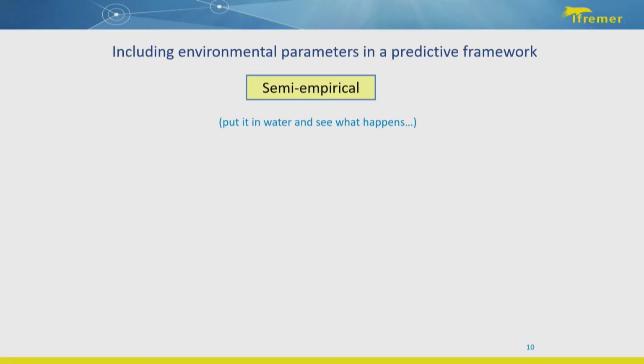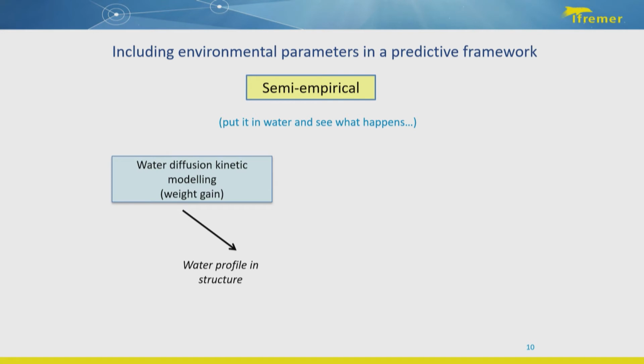So basically, we put the samples in water, in seawater, and see what happens. But to give you a little bit more understanding, we will do a first step. So the samples are immersed in natural seawater, and we will do a gravimetry test. So we will weigh the samples regularly, and like that we will get a weight gain, and it will help us to do a model of the water diffusion kinetics. And this will give you the water profile in the structure, which is, of course, absolutely necessary when you want to do a prediction.